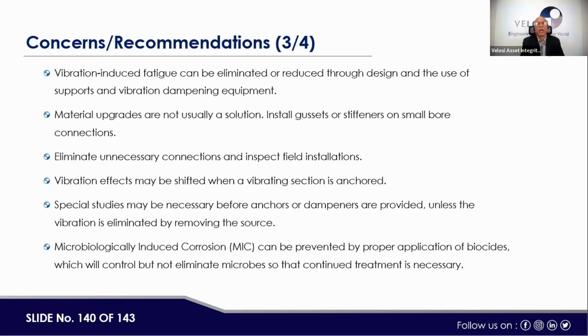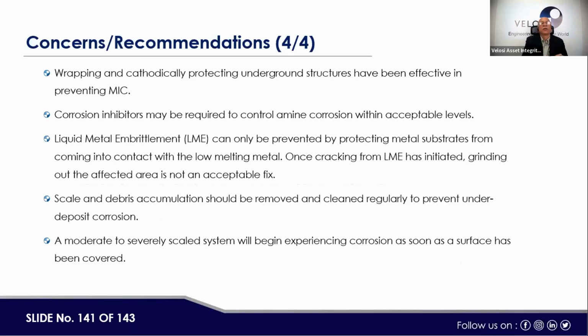Microbiologically induced corrosion, MIC, can be prevented by proper application of biocides, which will control but not eliminate microbes, so that continued treatment is necessary. Wrapping and cathodic protection of underground structures have been effective in preventing MIC. Corrosion inhibitors may be required to control amine corrosion within acceptable levels.